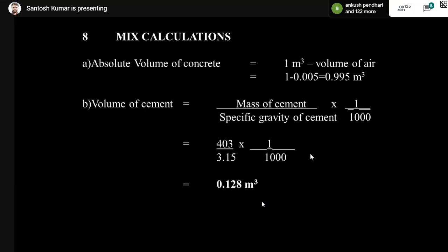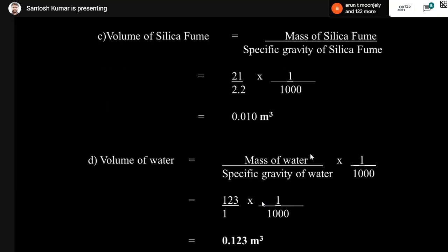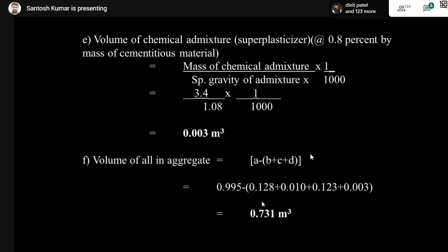That means you arrive at the volume of cement as 0.128 cubic meter. Now the volume of silica fume: weight of silica fume 21 kg divided by specific gravity of silica fume, multiplied by 1/1000. That gives you 0.010 cubic meter of silica fume. And volume of water: weight is 123 divided by specific gravity 1, you get 0.123 cubic meter of volume.